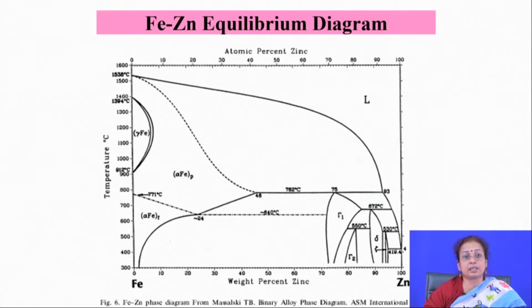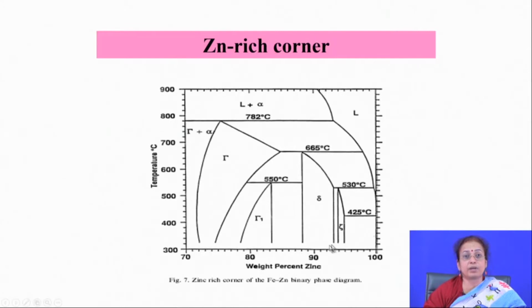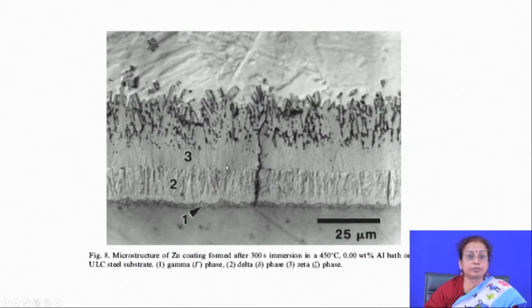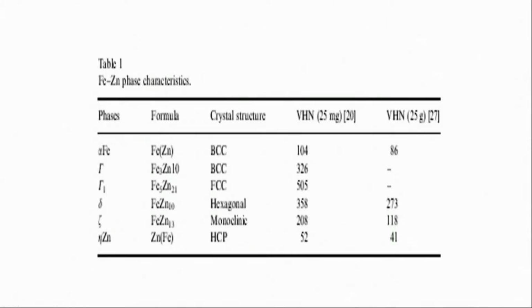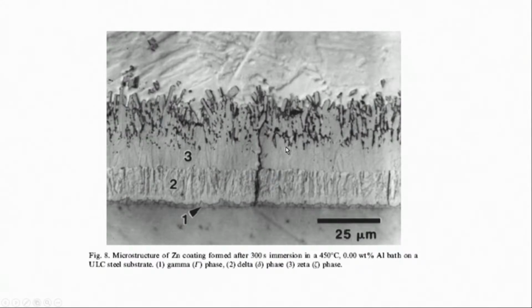So, when you keep a zinc coated, particularly galvanized, component in the normal environment, you will find there is formation of fine cracks after a long time. These cracks are because of all these different intermetallics which are formed. If you quickly go through them, you will find they have the typical HCP structure, monoclinic structure, FCC, BCC structures. Even though there are BCC structures, they are also not really as ductile as normal FCC. These phases form one after another, and because of their formation, when you keep the galvanized steel for a long time in normal environment, there is formation of fine cracks starting from the interface towards the surface.